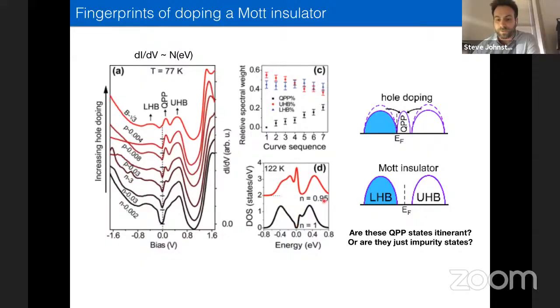And then upon 5% hole doping, we start to see the formation of this quasiparticle peak in between the gap, and it comes at the expense of the neighboring Hubbard bands. And this is again sort of reminiscent of this cartoon picture that I drew for you earlier in the talk. And so this is sort of the first indication that we're seeing something that looks like the spectral weight transfer that you would expect to happen.